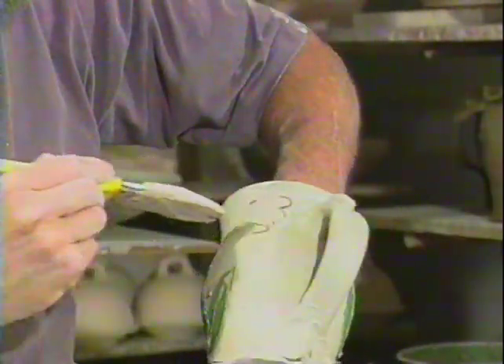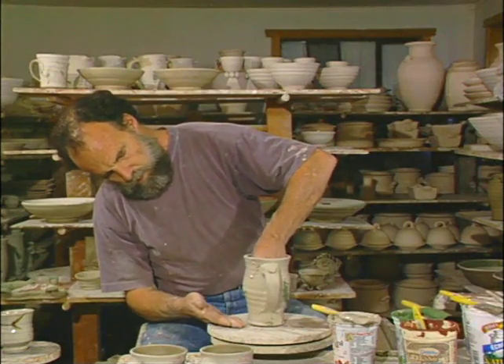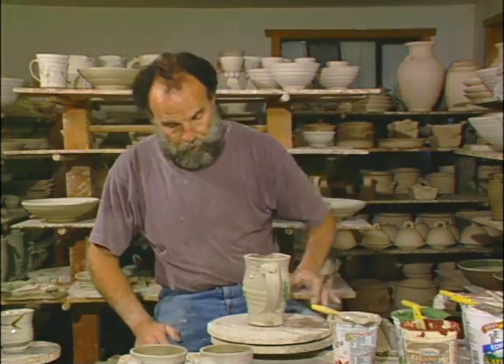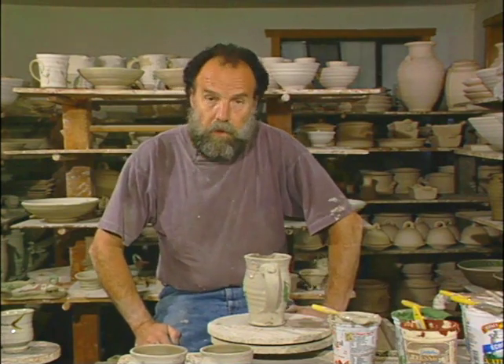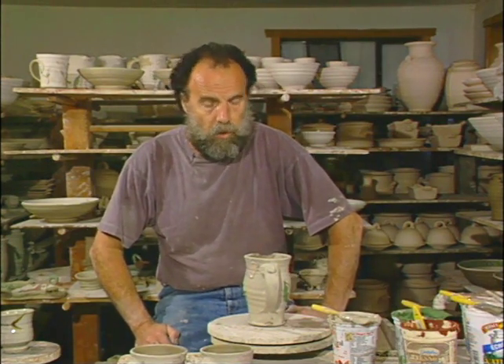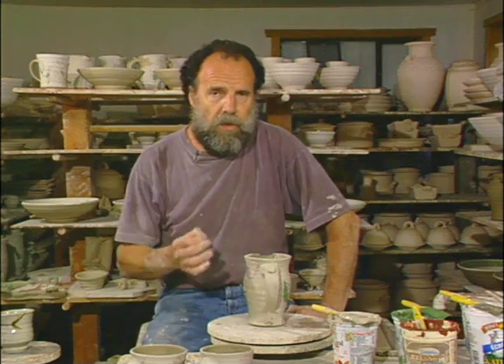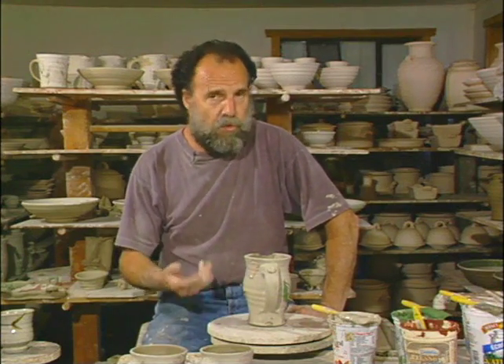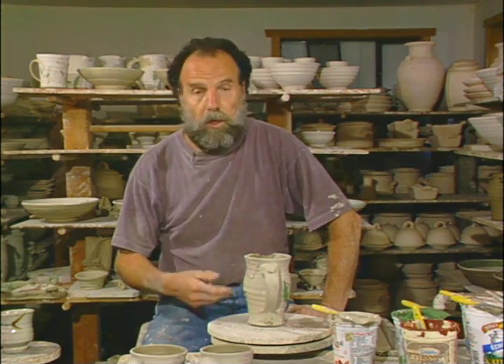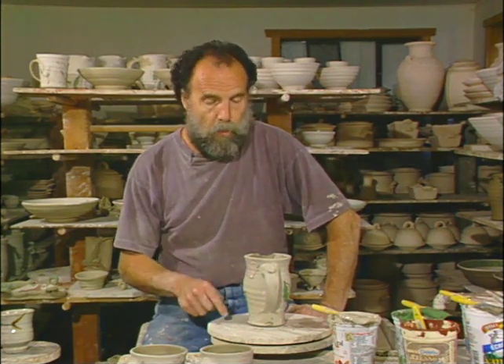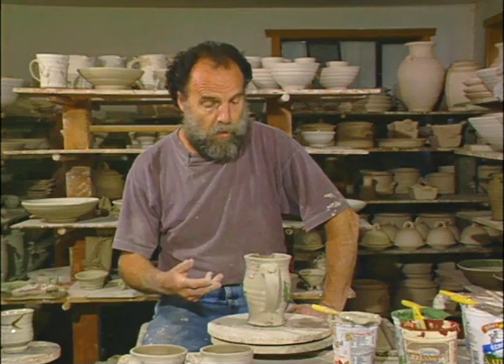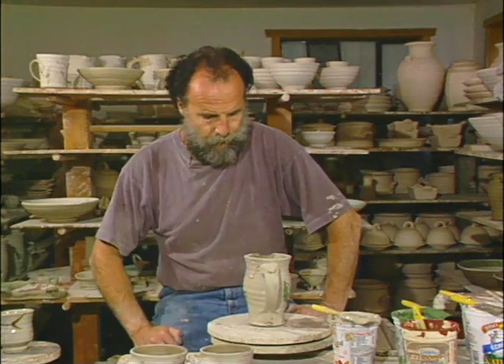Always got to be careful of handling the surface of a pot that's got slip on. You've got to remember that that slip is wet clay and easily smudged with your fingers. And that's that for that one. Let's put these pots aside now to let them dry. That should take 2 or 3 days under normal circumstances. We need them to dry thoroughly because the next step is to bisque fire them. Bisque firing is a lower temperature firing that we do preparatory to putting glaze onto the pots and doing a glaze firing.